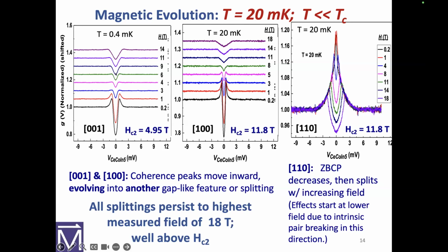I remind you, 6 Tesla is above HC2. There is no superconductivity in these upper figures. There's something going on that's splitting or growing, or whatever it is, with increased field. We also see that in the 100 direction, the A-axis direction. So here we have the cerium cobalt indium 5 at low field, just enough to drive the lead normal. We go up. Remember, we're above HC2, above 11, 14, 18.